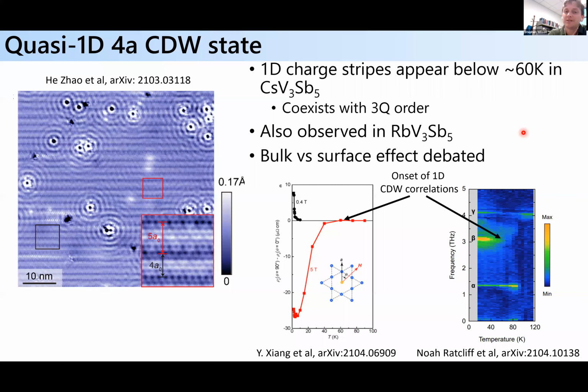Okay, maybe there's certain select regions where you can see it, but it's perhaps not as stable of an effect in the potassium system. And so I know that the STM groups perhaps are debating whether or not it's a bulk or surface effect, basically this charge modulation. I personally think that there are signatures that it is indeed a bulk effect, or it's a signature of something